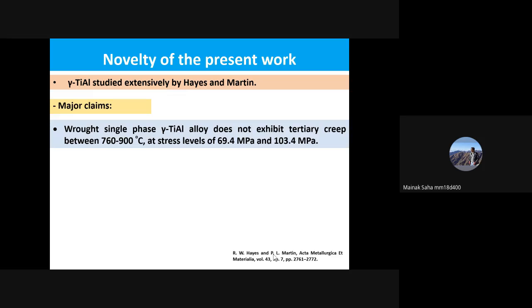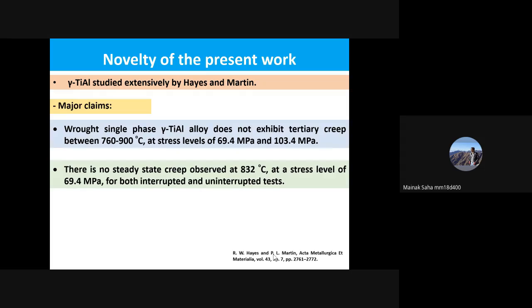Now, this was one of the major claims. The second claim was that no steady state creep was observed at 832 degrees at a stress level of 69.4 MPa for both interrupted and uninterrupted tests. In the literature by Hayes and Martin, the interrupted test was interrupted at 2 strains, that is 0.18% of the total strain to failure and 0.5% of the total strain to failure. The uninterrupted test was done till